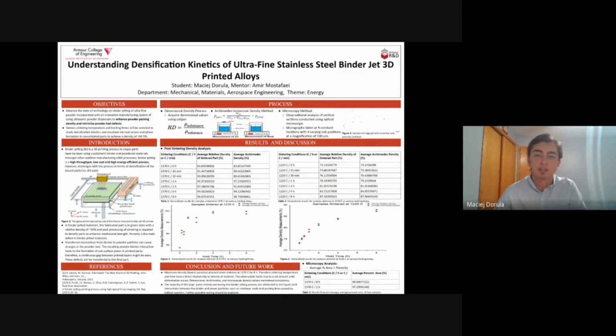In general, additive manufacturing has many advantages over traditional manufacturing, most notably the ability to produce complex geometries, virtually any geometry, without the need for a tool or a special setup. That being said, in binder-jetted materials, the fabricated parts in their green state, which we utilized, were determined to have a relative density of around 50% by using XYZ and mass measurements. Once sintered, a method of analysis known as the Archimedes immersion density process was utilized to more accurately determine the exact density of each sample. Further specifications are displayed under the process subsection shown.